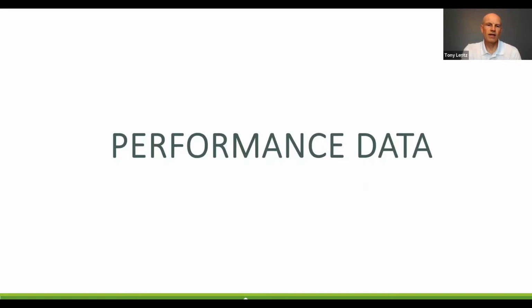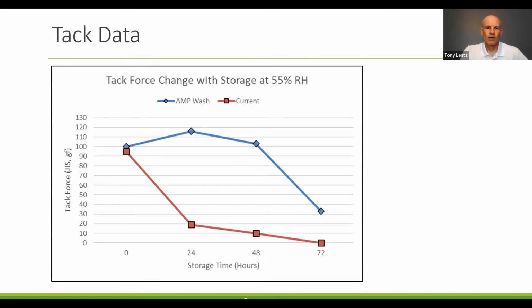Now here's performance data that we generate based on internal testing in our laboratory. Here's tack force change over time. So we have tack force on the y-axis here and storage time in hours on the x-axis. We run this test over a 72-hour period, and we test tack force coupons every day for 3 days.